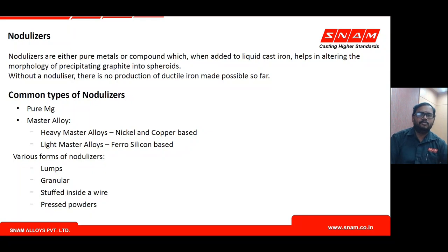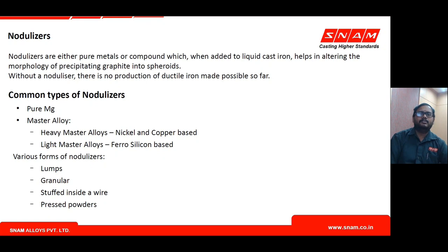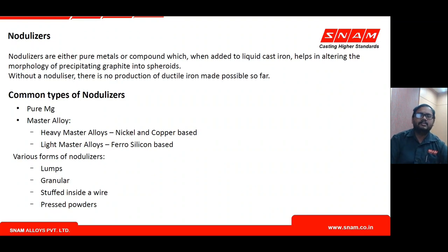There are different types of nodulizers available. Magnesium is the most common and most potent nodulizer known so far. Pure magnesium by itself is a nodulizing element. There are also magnesium alloys available commercially, classified into heavy master alloys and light master alloys. Heavy master alloys contain heavy elements like nickel and copper. Light master alloys are generally based on ferro silicon materials containing iron, silicon, magnesium, and other constituents.